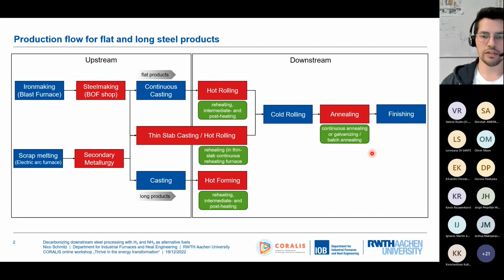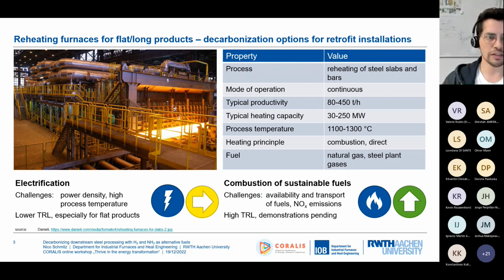For long products, a subsequent heat treatment is not typical, but it can also be the case. But we want to keep it simple today, not to go into a deep dive, so we look at those three main processes here. Starting with the reheating furnaces, and this is nearly the same for flat or long products. We have big reheating furnaces, which are there to reheat the steel slabs and bars after continuous casting. So on the left side of the picture, you can see such a furnace, quite big furnaces, up to 50 or 60 meters long, with really big productivities of up to 450 tons per hour in continuous operation.